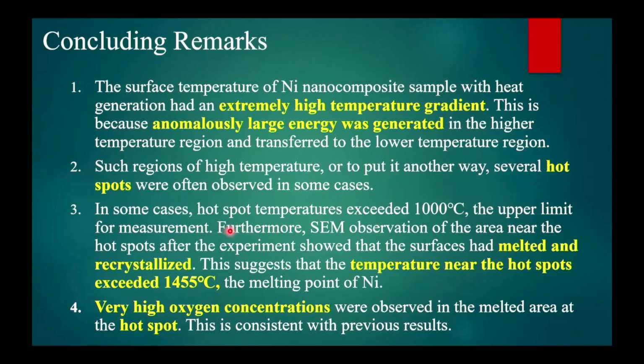cases. In some cases, hotspot temperatures exceeded 1,000 degrees centigrade, the upper limit for measurement. Furthermore, observation of the area near the hotspot after the experiment showed that the surface had melted and recrystallized. This suggests the temperature near the hotspot exceeded 1455 degrees, the melting point of nickel. And a very high oxygen concentration was observed in the melted area at the hotspot. And this is consistent with previous results.